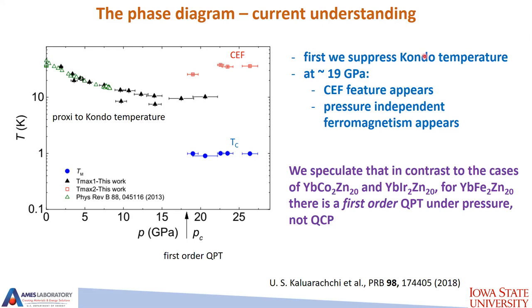Starting with suppressing the ordering temperature, then at around 19 GPa or so, a feature corresponding to the crystal field appears. At more or less the same temperature, pressure-independent ferromagnetism appears. So somewhere here or above 19 GPa, ytterbium is purely 3+, and behaves as you know 3+ behaves, not like a strongly correlated material would. So in contrast to the cobalt, rhodium, iridium members of the family, in the case of ytterbium iron zinc 20 under pressure, we have a first order quantum phase transition under pressure, not a quantum critical point.